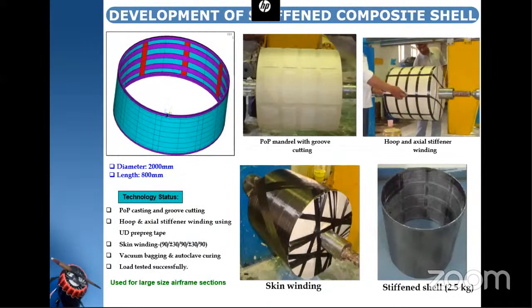This is another important element which we have made by using a filament winding technique. Here you can see a grid stiffened plate which is made by using a POP mandrel with groove cutting. So we can place the fibers in the grooves and then subsequently on the outer periphery so that we can make grid stiffened shells. With these shells, we can reduce the weight of the component and achieve the desired properties. So these are the new concepts which we are extensively practicing for the manufacturing of airframes.